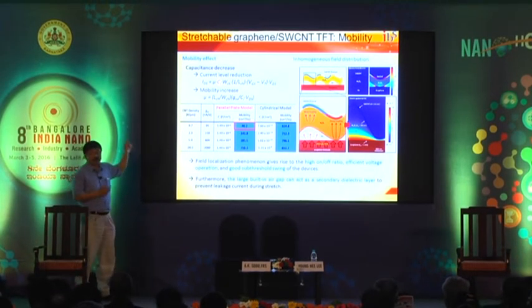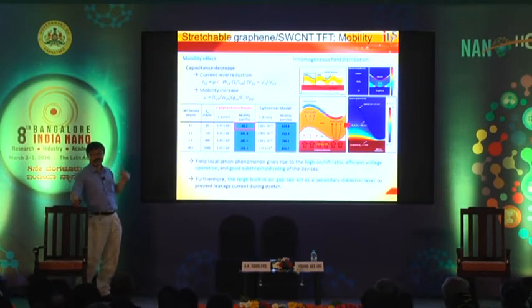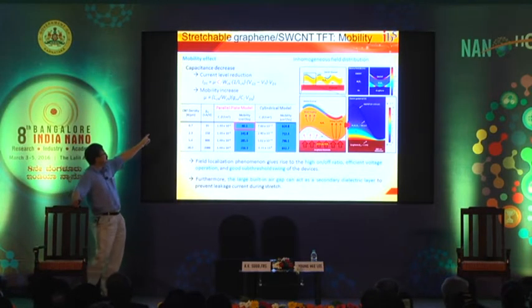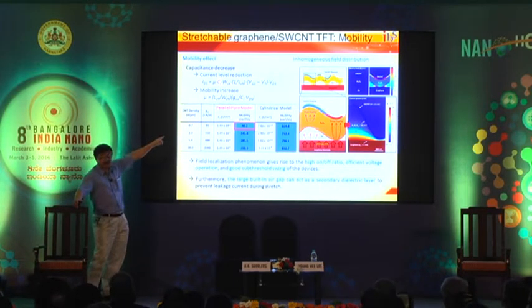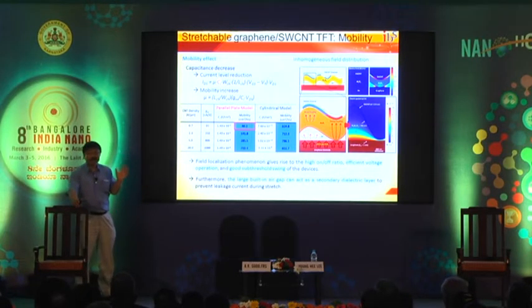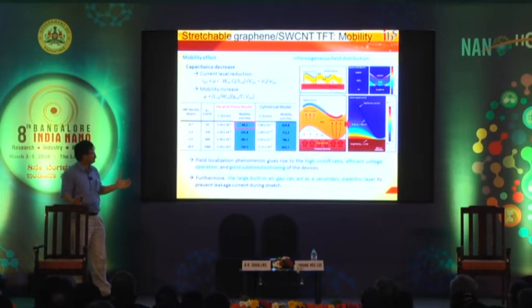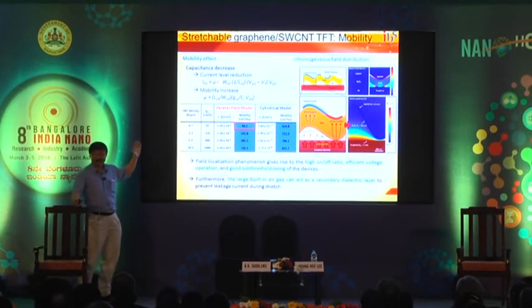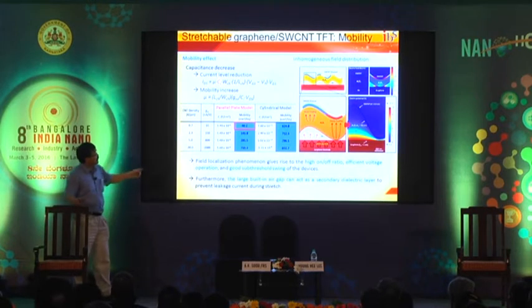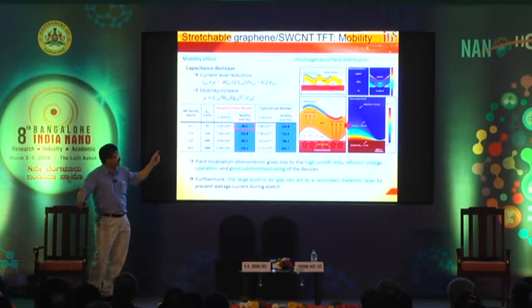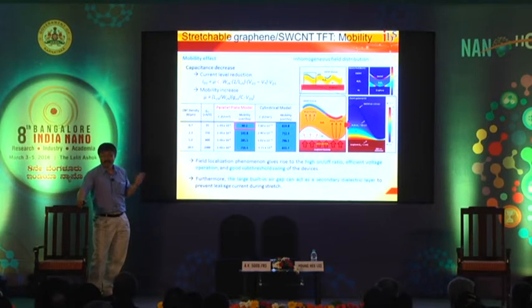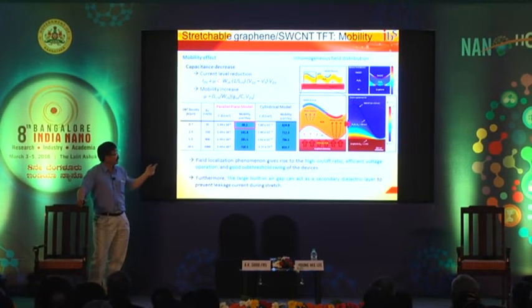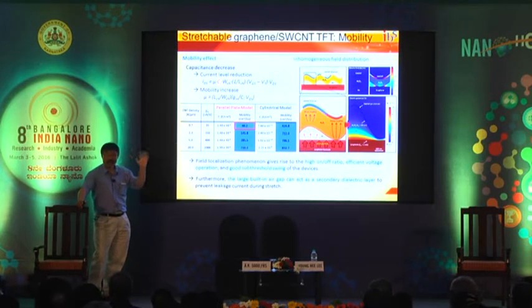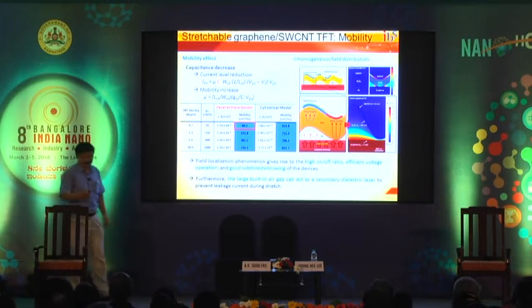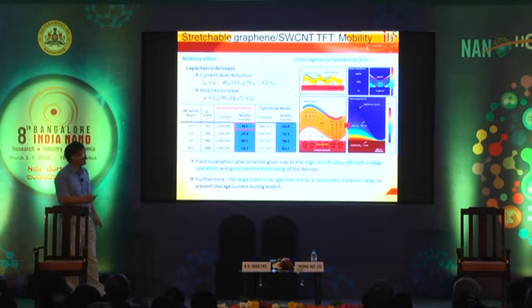When you consider this on current, of course, this capacitance decrease actually decreases the on current, but mobility is actually canceled out by this denominator capacitance. So the mobility is quite independent of this air gap. So this is quite lucky, because then we can maintain a high mobility as well. And then also, because we use a CNT as a channel material, there is another advantage that we have this very low subthreshold swing because of this special localized field emission that controls these carriers very efficiently. So this one has certainly some advantages.